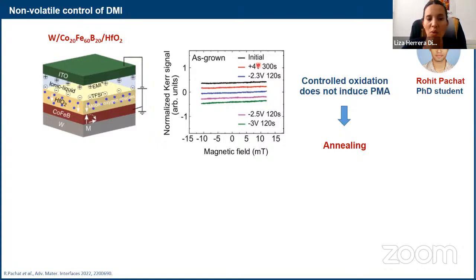So this is what we learned. We know that tungsten is polycrystalline. It's in the beta phase. So it's not quite the same as we had before, an entirely amorphous system. So what we see here is that we cannot induce PMA with oxidation in this system. So then what we thought is that, well, that's why people anneal it to get PMA, so that you can get this crystallization of the cobalt iron boron and this nice quality interface with the tungsten.